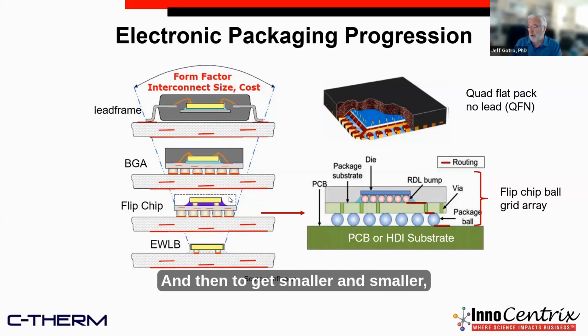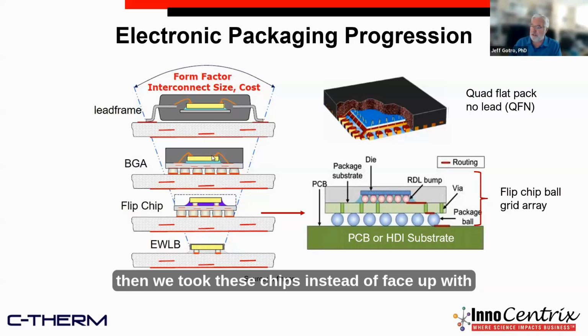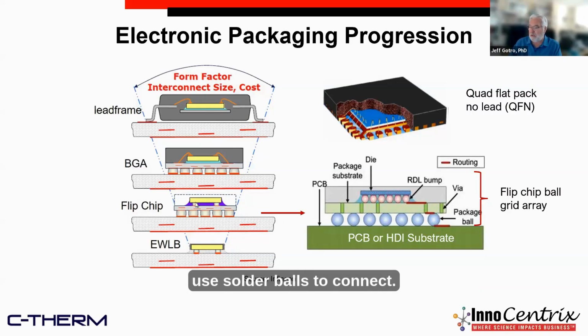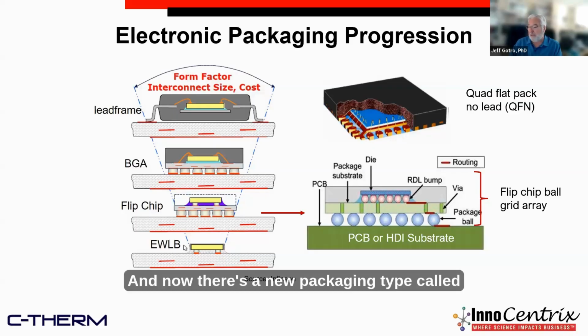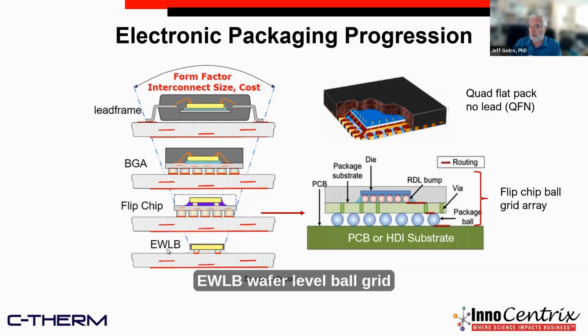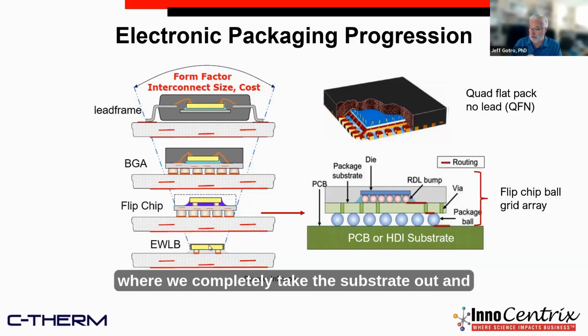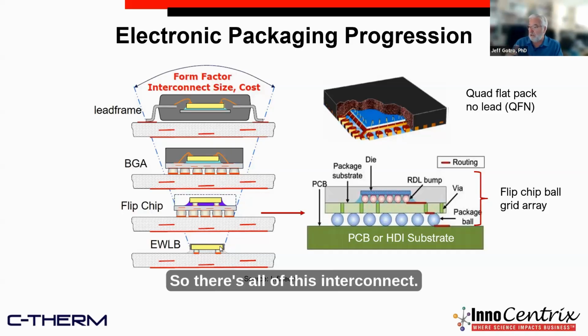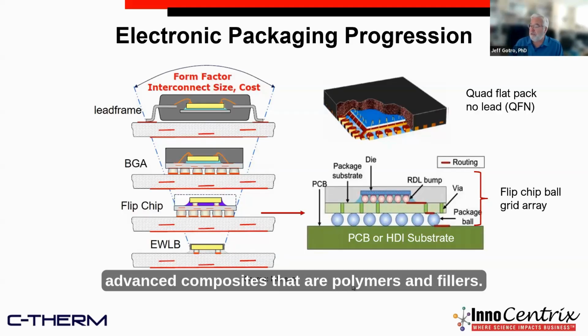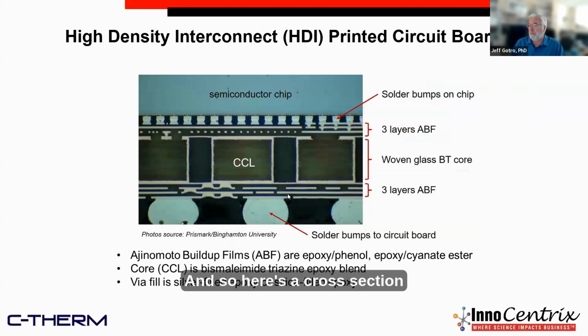And then to get smaller and smaller, we took these chips, instead of face up with wires, we flipped them over and used solder balls to connect. And now there's a new packaging type called eWLB, wafer level ball grid array, where we completely take the substrate out and we use high density wiring right here on the top of the chip. So there's all of this interconnect, and it's all pretty much enabled by these advanced composites that are polymers and fillers.